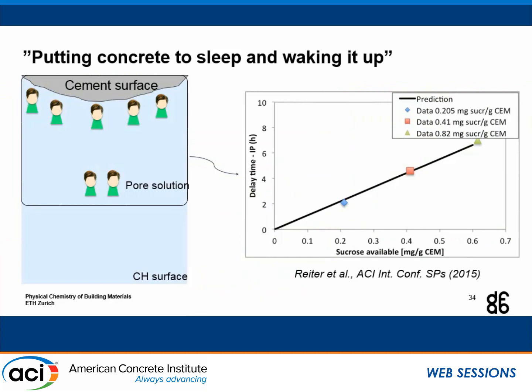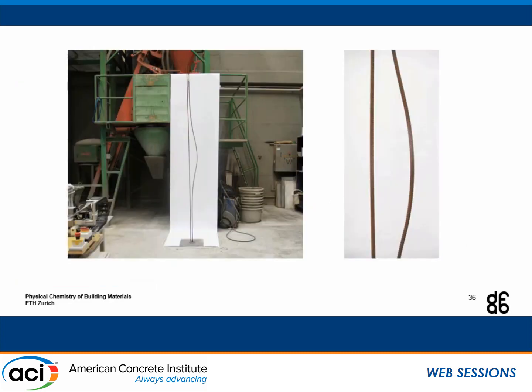The concept introduced by Lex is basically putting concrete to sleep and waking it up. Lex makes nice animations showing the cement surface with sucrose — the green guys — adsorbed to the cement surface. One way to wake the concrete up and start hydration is to introduce a surface that is more attractive, like a calcium hydroxide surface, to pull the sucrose away. There are also other ways of doing it using active accelerators, and which phase gets accelerated depends on what accelerator you're using.